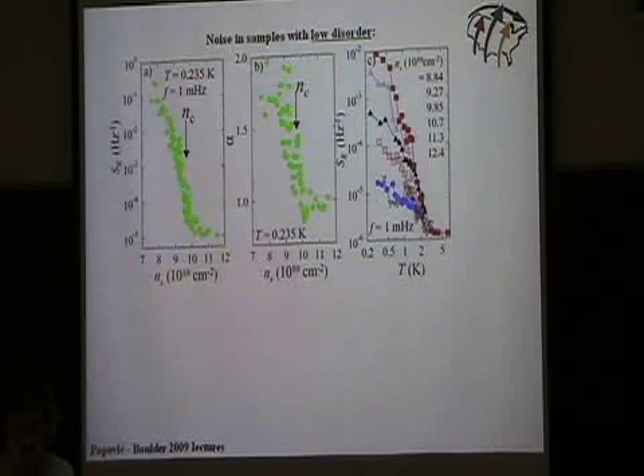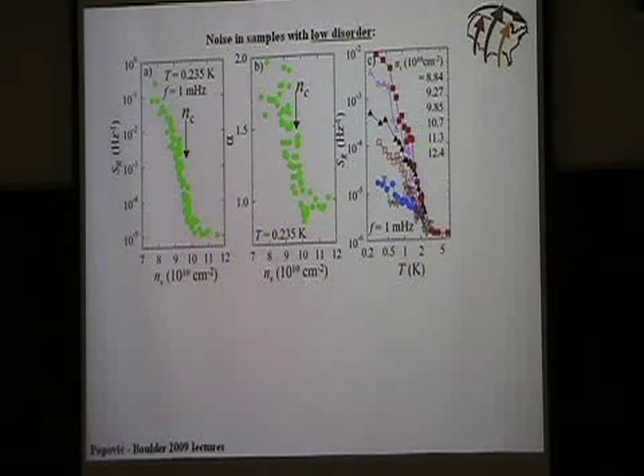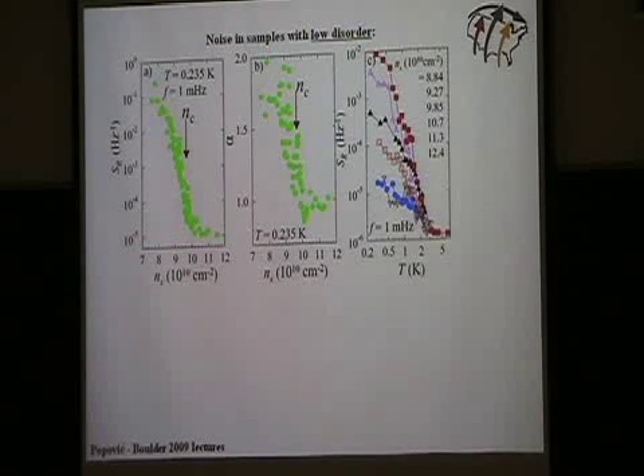Then you repeat everything here. So here we are looking at the magnitude of the noise at some low frequency as a function of density. Again, you see that there is some density where noise goes up rapidly over a small range of densities. The same thing happens with the exponent alpha of the noise. It goes from 1 to a much higher value. And also the temperature dependence is the same as in low mobility samples. It increases again exponentially at the lowest densities as temperature goes down.